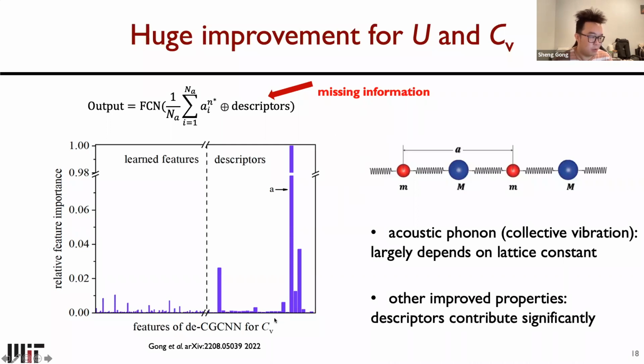So for the phonon related property, if we only consider acoustic phonon, which is collective vibration of all atoms in the unit cell, then if we go to a textbook of solid state physics, we will know that this acoustic phonon largely depends on the lattice constant. And in addition to the phonon related properties like heat capacity, for other improved properties in this figure, we also observe that descriptors contribute significantly in the distribution of feature importance.